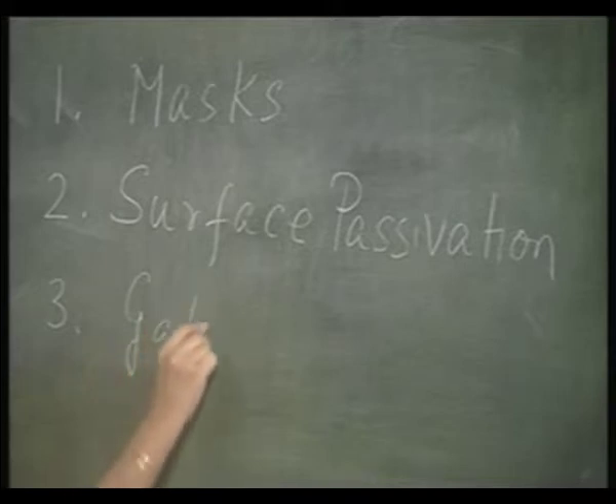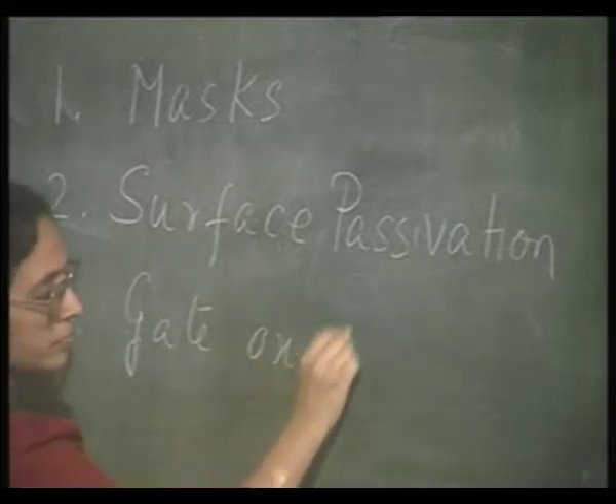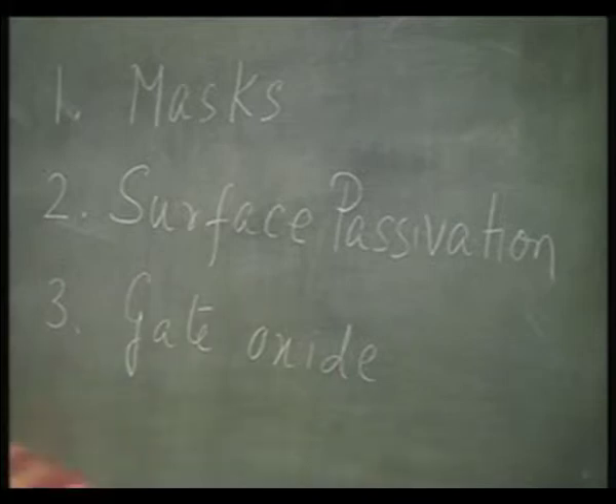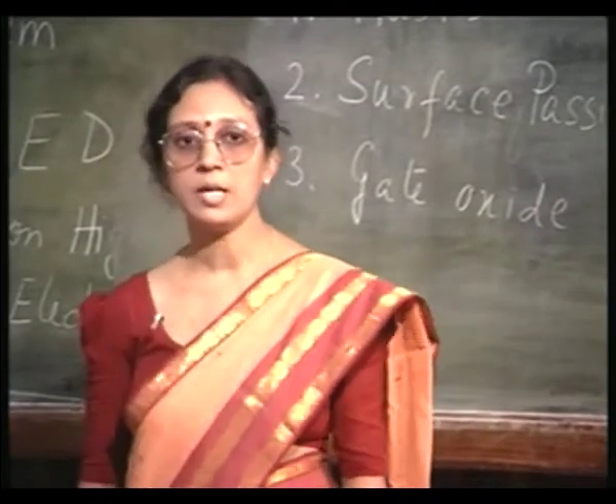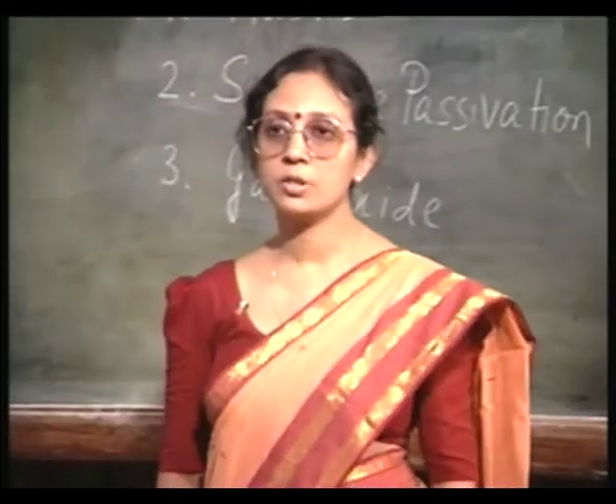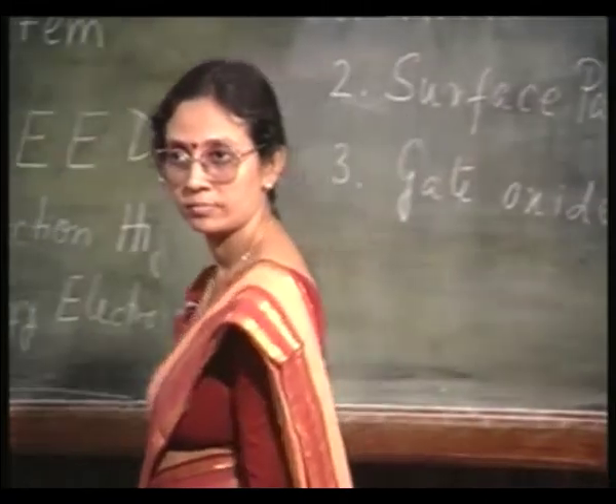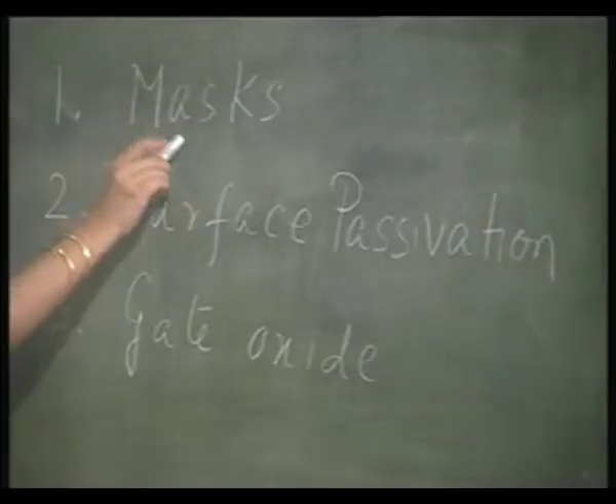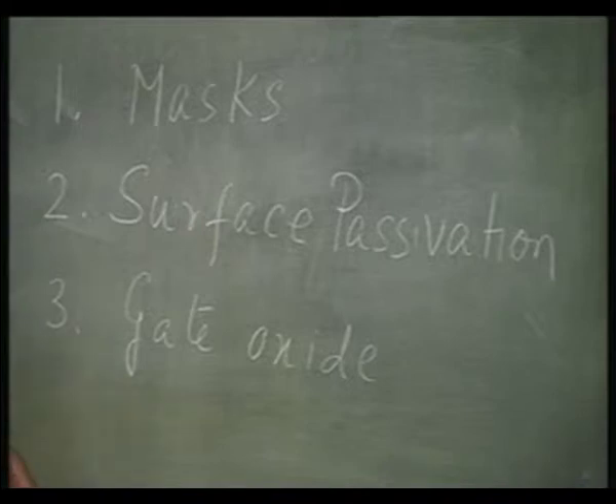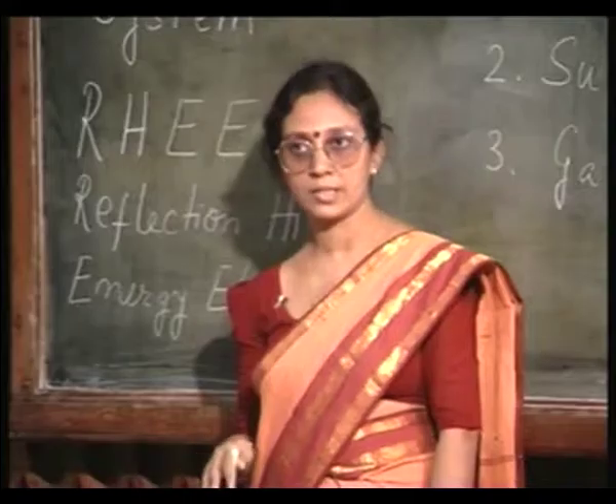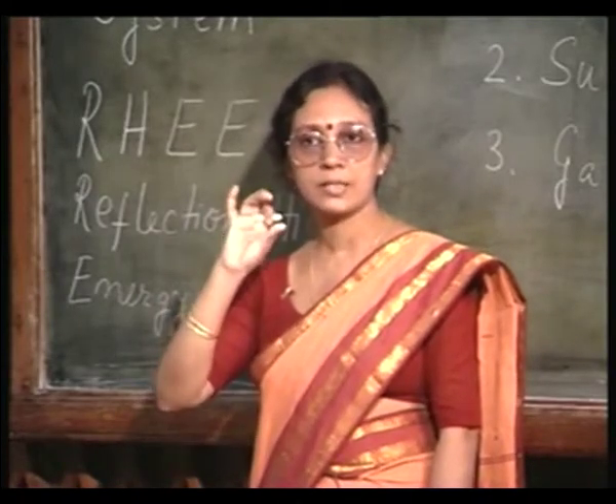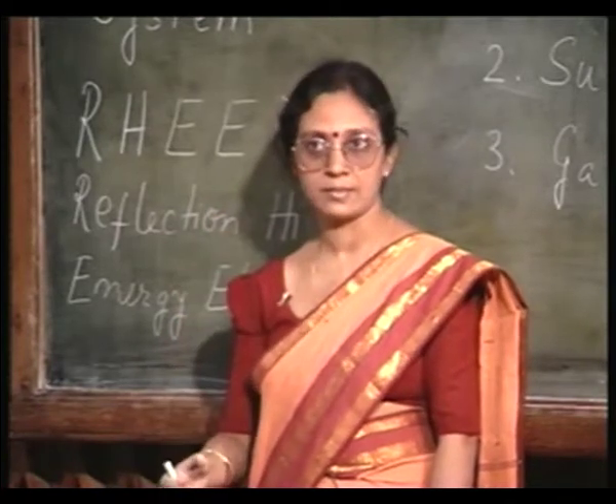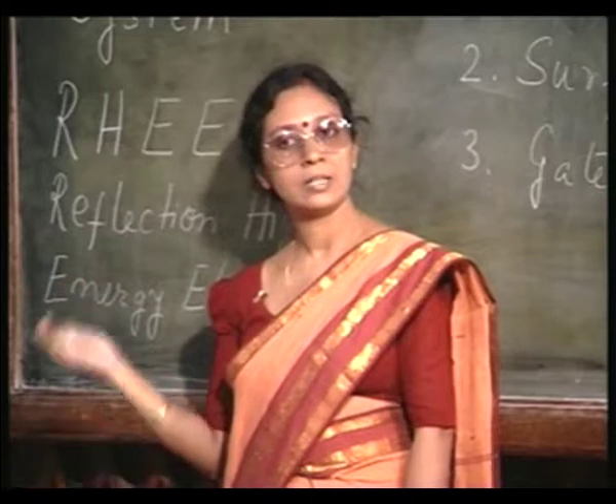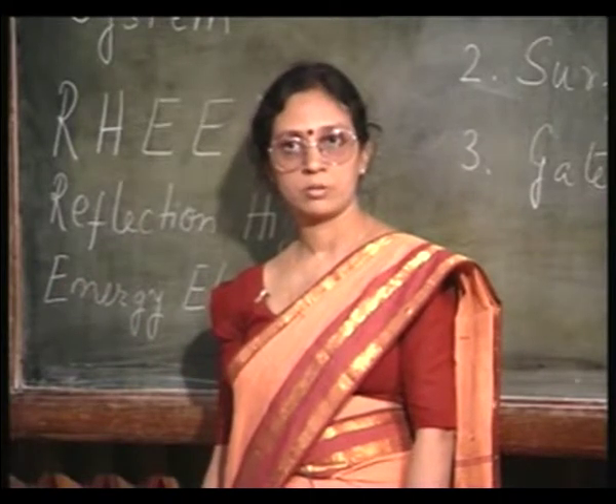So, my requirements are different. You see, when I am talking about gate oxide in a MOS field effect transistor, I am more worried about the quality of this oxide. On the other hand, when I am talking about masks, I am more worried about the thickness of this oxide, because I need a requisite thickness. I know that I will follow it up with a certain doping step. So, during that doping, the oxide thickness must be such as to mask during that dopant incorporation.